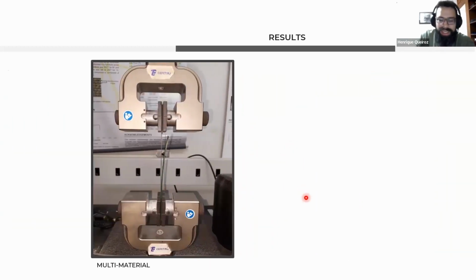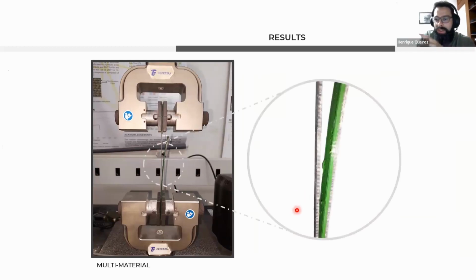And so this is interesting. This is one of the multi-material specimens that we tested. And when it failed under the tensile test, the ABS debonded from the PLA, and you can actually see water inside of it, like big drops of water, which is interesting to see.